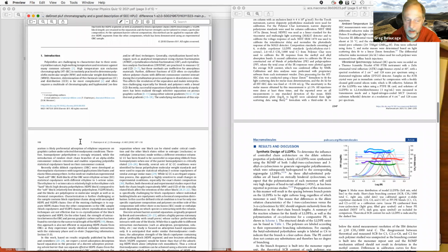So anyway, the difference between SEC and HPLC: this one is basically looking at this random path thing. So that's basically like diffusion. So that's entropy. Notice how random is the motion of the particle. Is it ballistic, not random at all? So entropy is 0, or is it this big random path where entropy is some number, right? The less the particle searches out through the sample, the less entropic it is. So basically, size exclusion is an entropic measure.